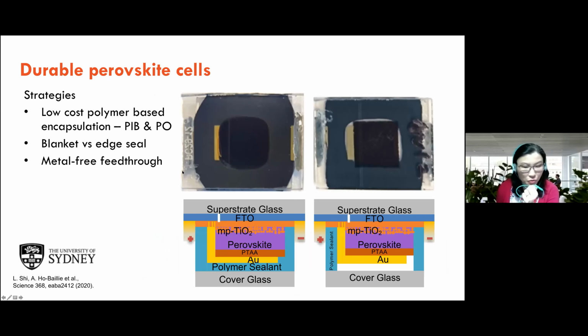Okay, so what do we do with the information? You have the signature products. They're like fingerprints that you can use to evaluate the effectiveness of the encapsulation schemes that we developed. We use low-cost polymer, which is PIB or PO, and we use two techniques. One is a blanket encapsulation, where you can see the polymer covering the entire cell, or we use the edge seal, where you have the polymer just going around the cell, and therefore you have a void there. And we use metal-free feedthrough, so we're relying on the FTO to do the feedthrough.